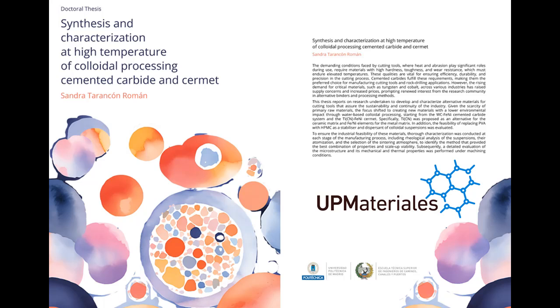Absolutely. Okay, so now they have those carefully prepared suspensions. Let's talk about the atomization process in more detail. What exactly happens during that step? Figure 2.4 shows a schematic of the setup. It involves spraying the liquid suspension through a very small nozzle. They used one with a 1 millimeter opening into a heated chamber. The chamber is filled with hot air, which rapidly evaporates the water in the droplets. As the water evaporates, you're left with these tiny dry powder particles. So it's a carefully controlled drying process, essentially.